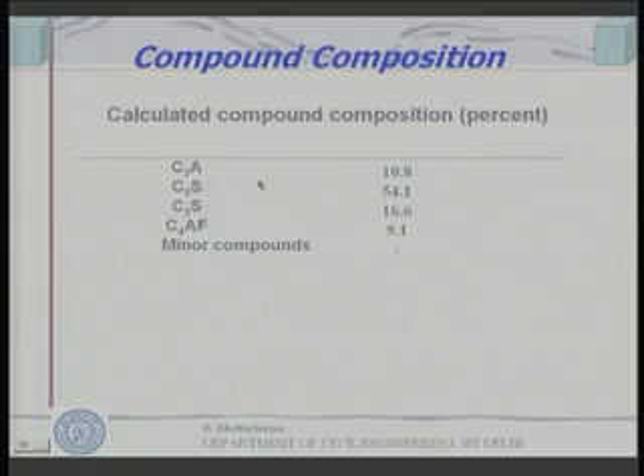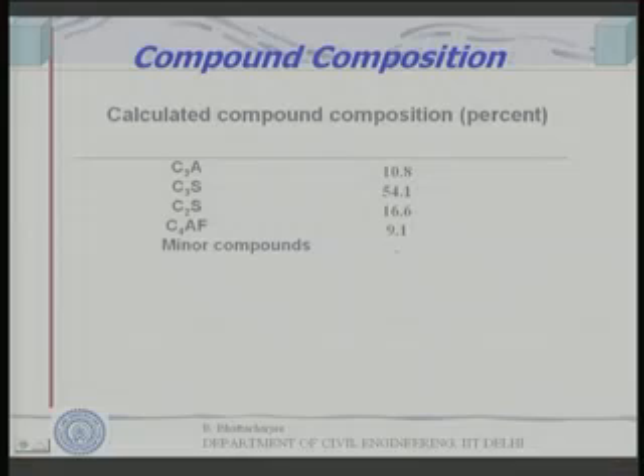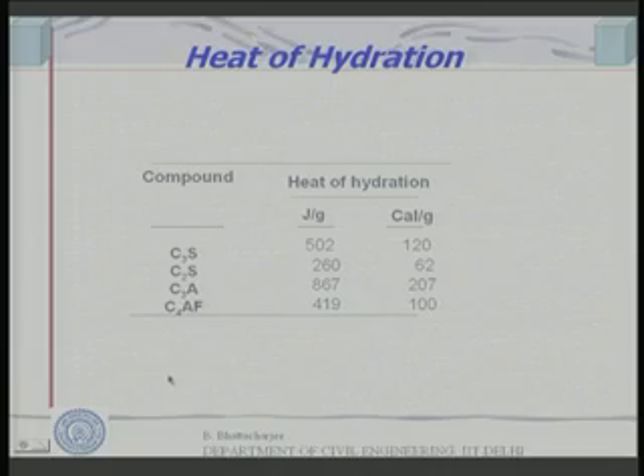assuming calcium oxide is for OPC 60 to 67%, which was shown earlier, in one of those earlier slides. So, you can see that roughly C3S is 54, that is the maximum percentage, C2S is about 17, C4AF is 9 and C3A is 11%. So, one can calculate the oxide composition, and from the oxide composition one can calculate the compound composition.